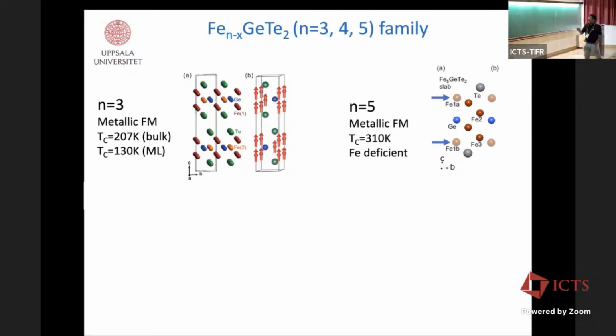Anyway, the material looks like this. So this is a bulk structure. You see the bulk unit cell when it is N equal to 3, Fe3 germanium telluride, a metallic ferromagnet in bulk. Tc is 207 Kelvin. In the monolayer, it's a pretty high Curie temperature, 130 Kelvin. So you see that the green atoms are tellurium atoms. They are basically on the outermost layer. Then you have iron atoms, and then in the middle, you have germanium atoms.